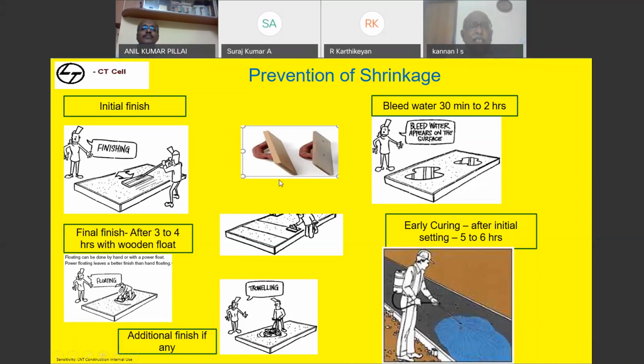So ask the mason to tap the entire surface of the slab with the wooden float in a circular manner. You need to finish it. If any secondary finish is needed with additional finishing, do it. Start curing after 5 to 6 hours. It is not that only after 24 hours or 12 hours the concrete needs to be cured. When the concrete attains touch hard state, you can start.